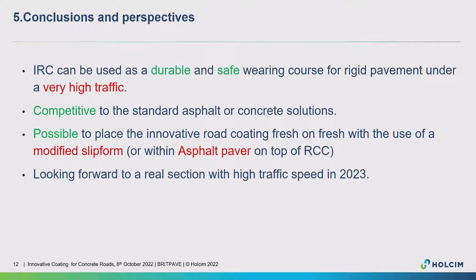So rapidly, for some conclusions and perspective. Again, through this study and investigation, we can say that it can be used for durable and safe wearing courses for the rigid pavement under very high traffic. It can be competitive to the standard asphalt or ordinary concrete solutions. It is possible to place this concrete fresh on fresh or fresh on dry with the use of existing equipment like the slip form or asphalt paver, or we can easily modify the slip form if you want to do only one pass for the 2-layer placement.